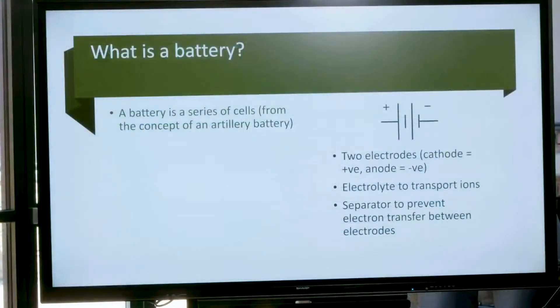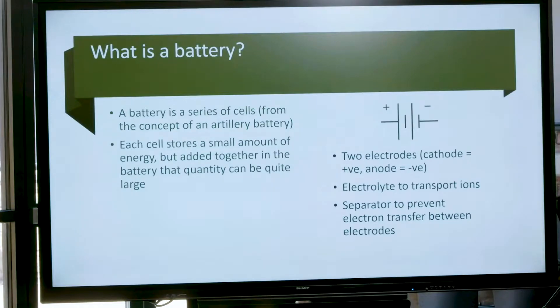You can have different types of charged ions — for example, fluoride ion batteries. A vital part of the design is a separator, which keeps the two electrodes apart, ensuring there is no electrical conductivity between them — only ionic conductivity. In normal low-temperature lithium or alkaline batteries, this is a polymer or mesh that is dielectric. In our battery, we use a solid electrolyte, which acts as both electrolyte and separator, carrying only ions and allowing no electronic transfer.